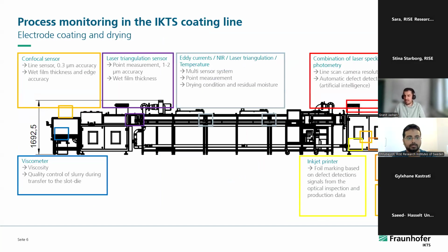This is our coating line. This is a tape casting line. During the whole process, starting from the mixing, we can check inline the quality of the slurry, the viscosity. Then we check the wet film thickness and edge accuracy. Then we have eddy current sensors where we track and check the drying condition and the residual moisture. Then in the end, to detect defects on the electrode surface, such as agglomerates, line defects or impurities, we have a combination of laser speckle and photometry. All this is done in an automatic way, and we also get feedback when something is going in the wrong direction.